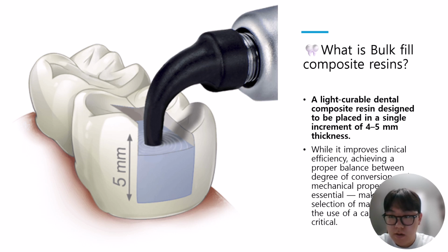Before we go into the study, let's first take a look at what bulk-fill composite resins are. These are light-cured dental composites that can be placed in 4 to 5 mm increments, which is thicker than traditional composites. They are designed to save time and reduce the risk of voids between layers. But since we place them in bulk, it's important to evaluate how well they cure and how strong they are.